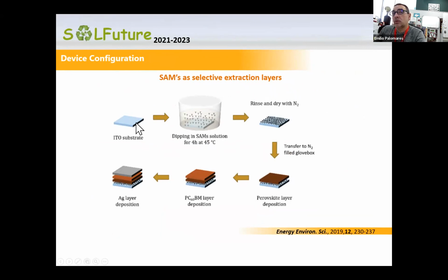So you get the ITO, or your transparent conducting oxide, you dip in a solution containing the molecules, you rinse with the same solvent, you dry with nitrogen, and then you do all the steps towards the fabrication of the solar cells. In fact, the people in Germany also use this process to make the silicon and perovskite tandem solar cells using the small self-assembled molecules as contacts, and they achieve the record efficiencies of these tandems.